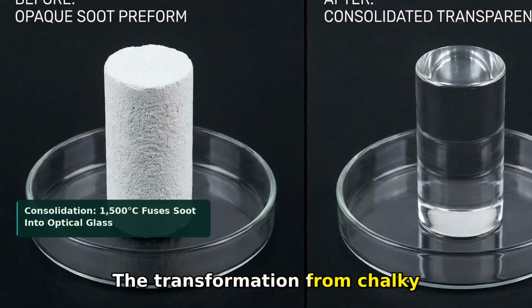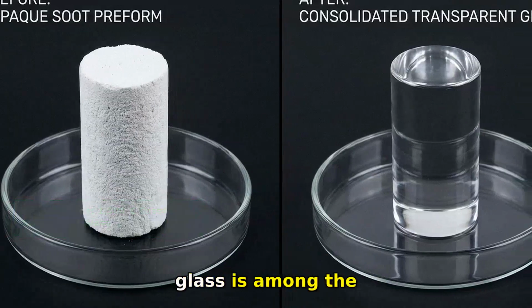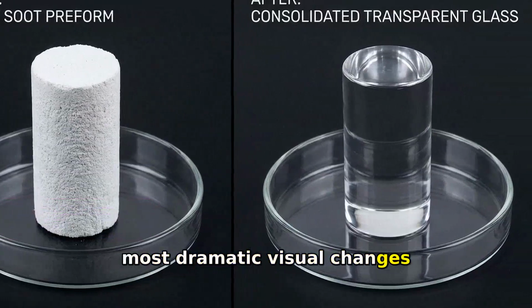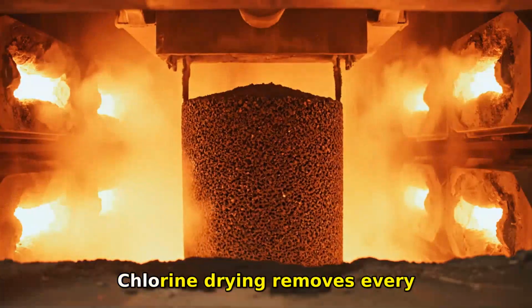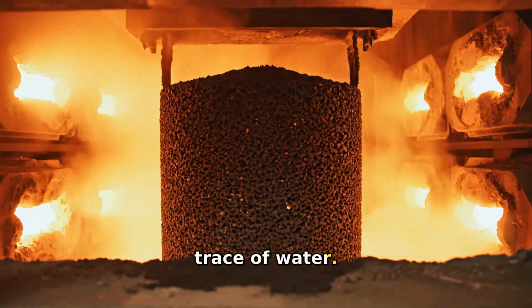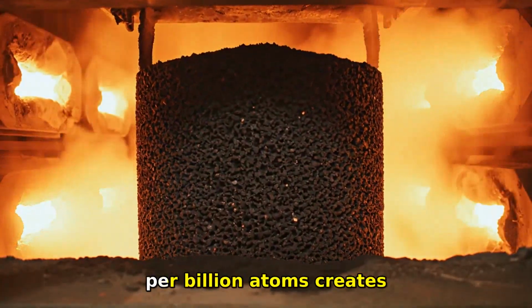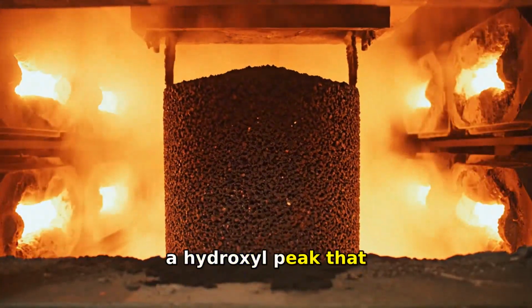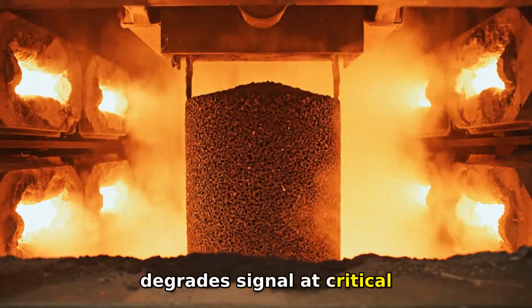The transformation from chalky soot to crystal clear glass is among the most dramatic visual changes in the entire process. Chlorine drying removes every trace of water. A single water molecule per billion atoms creates a hydroxyl peak that degrades signal at critical wavelengths.